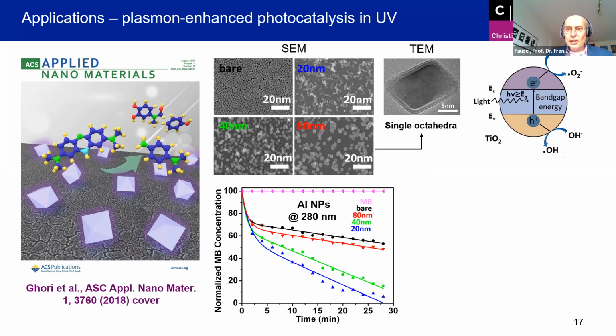Our specialty is not to make this particle-based, but to develop sputter processes where we deposit highly photoactive titania and other films. Here's an example of normal titania where we manage to get a large effective surface for very active photocatalysis. And we combine this with our UV plasmonic approach, which I mentioned earlier. So we decorated the surface. This is a sketch here, and this is a real TEM image. We decorated the surface with nanoparticles of aluminum, which are plasmonically active. And so we use the plasmonic enhancement to enhance the photocatalytic activity.